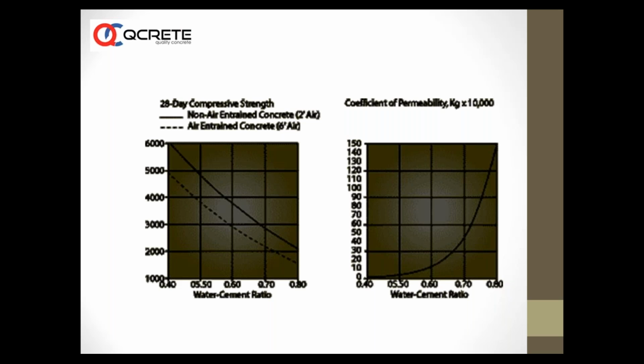Any construction engineer, QA/QC engineer, whoever is involved in production or reception of concrete, or in any form associated with construction, needs to always remember these two graphs. The first graph shows that as the water cement ratio shifts to the right, the strength comes down. The other graph, almost a mirror image of the first, is water cement ratio versus permeability. As the water cement ratio goes up, permeability goes up, and impermeability is highest when the water cement ratio is 0.4 and below.